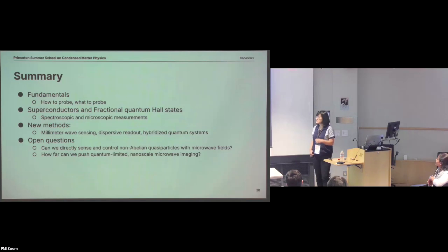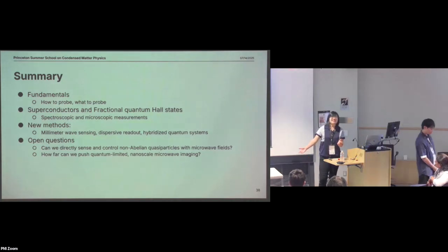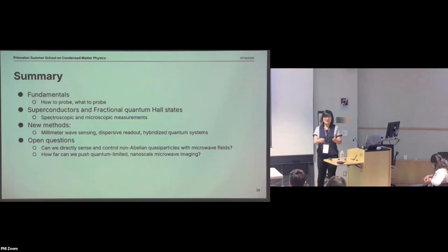Thank you for your questions. So first of all, for your first question, why the width of the MIM signal that we saw is wide? Well, the short answer is the screening is poor. If your screening is very good, then you would be able to see an edge on the length scale of a magnetic length. But in our case, we deliberately designed it to have a poor top gate because we want microwave to go into it. And we had a sample with not high enough mobility. So that's kind of the status of using twisted samples to see this type of fractional state. The mobility is not comparable with graphene monolayer or gallium arsenide. So then you have a lot of loss in that case. So these two together just made the edge state wide.